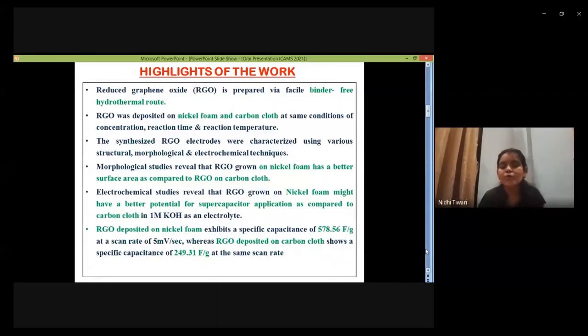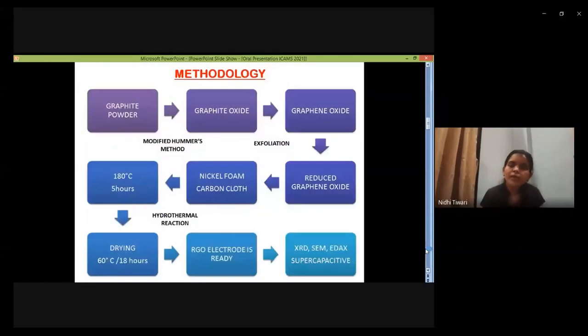After synthesis, the structural, morphological and electrochemical characterizations are done. From morphological studies, it can be seen that the surface area of RGO on nickel foam is greater as compared to that of RGO on carbon cloth. The electrochemical studies in 1 molar KOH give the capacitance of RGO on nickel foam as 578 farad per gram, whereas RGO deposited on carbon cloth gives a specific capacitance of 249 farad per gram. So the difference can be noticed here itself.